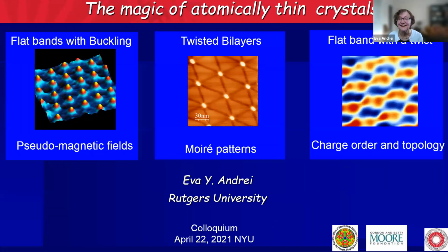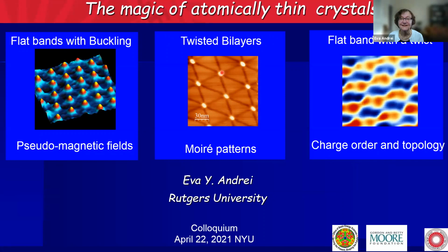This AA region. Wait, I don't see where you're pointing. You see the AA regions here? Do you see my screen? I see your screen. I don't see a pointer. You see my laser pointer here? Oh, now I do. Okay, yes. You see they shrunk tremendously, and there's a huge amount of strain, and we measure that is embedded in it because it really doesn't want to be AA. So there is always strain in these things, but it's because of the structure.